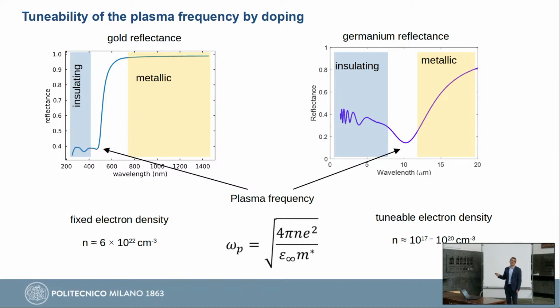So the transition between these two behaviors is set by the plasma frequency, which more or less corresponds to this point here. You can make a very simple free oscillator model and get the value of the plasma frequency, and we see that this depends on the density of the carriers you have in your system. So for gold, this density is fixed. It's roughly 6×10^22 per cubic centimeter. So you cannot change it. So gold will work nicely only in this visible range. If you try to obtain the same properties in the infrared, which is where we want to go, you will fail. But now let's say if we use a semiconductor, what will happen?